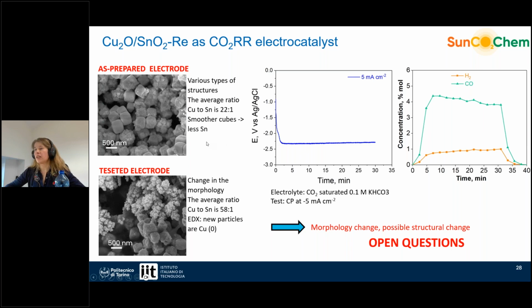So before we were able to perform the in-situ, because we did not have the improved modified liquid cell configuration, we did test this catalyst before and after electrocatalysis, and we observed that part of the material changed in the morphology, and actually we observed also some structural changes. And we observed also that some of the material remained not very much affected.